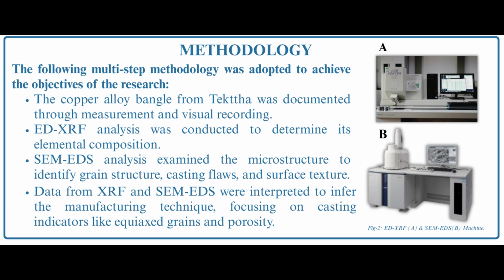To achieve these goals, we adopted a carefully structured multi-step research methodology. We began by documenting the bangle through measurement and visual inspection to understand its physical characteristics. Following that, we used energy dispersive X-ray fluorescence, commonly known as ED-XRF, to determine the elemental composition. We then employed scanning electron microscopy paired with energy dispersive spectroscopy, or SEM-EDS, to examine the internal structure, surface texture, and manufacturing traces. Together, these methods provided a comprehensive understanding of both the composition and craftsmanship involved.